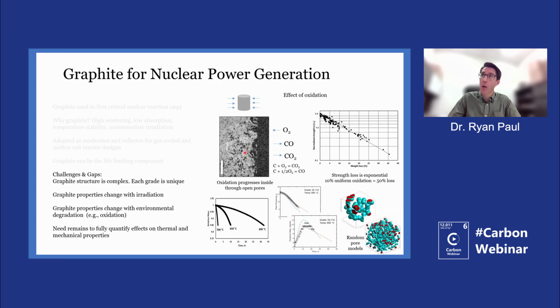So we need to understand not only the overall loss of carbon and graphite from the structure, but how the pores grow at some depth inside the material, because as this plot suggests, there is an exponential decrease in the strength of the graphite article with weight loss. Roughly speaking, about 10% oxidation would cut the strength in half. And so even a few percent oxidation can really start to change the integrity of that graphite material.